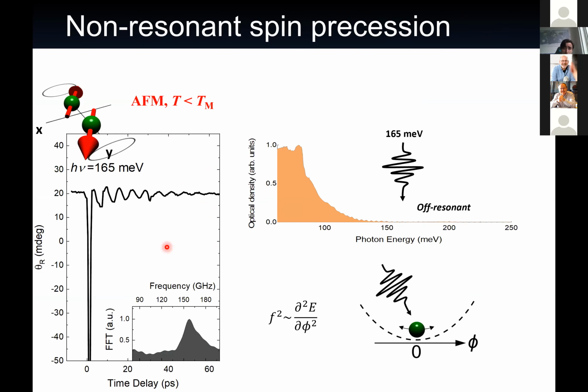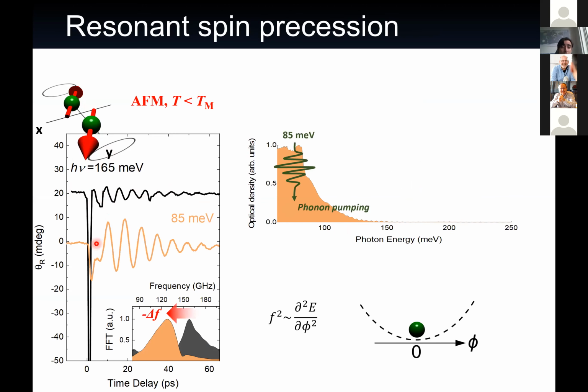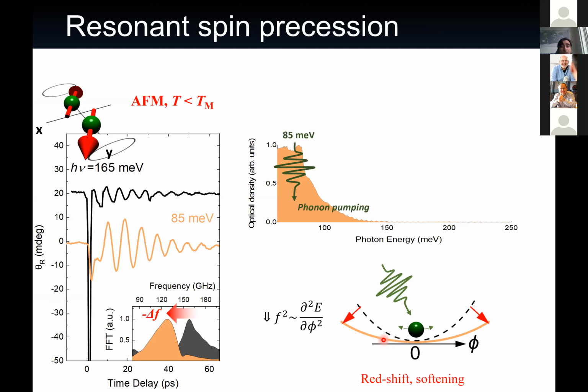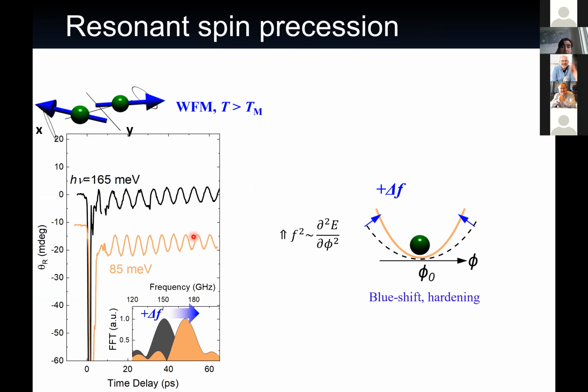When we are non-resonant with the lattice mode with our pump, so we're not exciting the crystal lattice here, we are only exciting Raman processes. We can indeed activate spin precessions and measure an oscillation frequency of our spins, which corresponds to the Raman spectroscopy of this material. The surprise comes when you excite in resonance with the phonon modes of the material. You again excite a spin precession, but now with a highly renormalized frequency. The frequency of this oscillation is redshifted to a larger extent. This indicates directly that by exciting the lattice, you are softening the magnetic potential, so you are changing the magnetic interactions in the system.